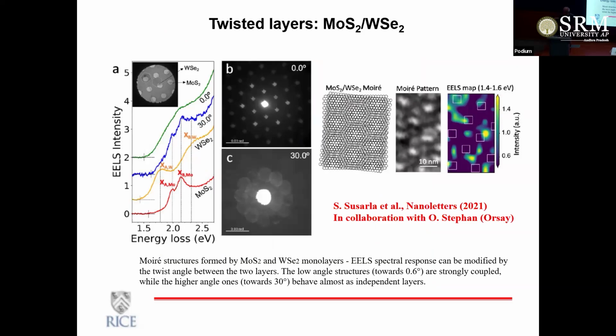And then came this whole creative approach where they were really trying to twist the layers once you stack. There's a whole area that has emerged called twistronics, and I'm sure many of the audience here who have been working in this area know about this. The idea of twistronics is that because the layers are atomically thin, if you can control the stacking order between the two layers, then you can get a specific type of electronic structure of these stacks. People have found superconductivity in a bilayer stack of graphene. People have found exotic optical properties when you stack at a certain angle. So twistronics has really become a tool in engineering.